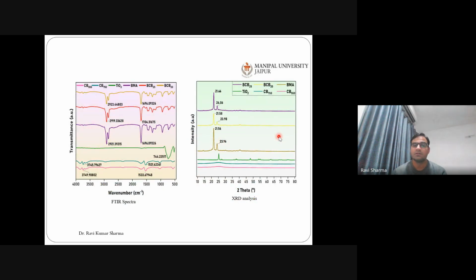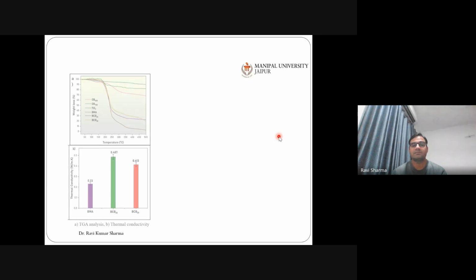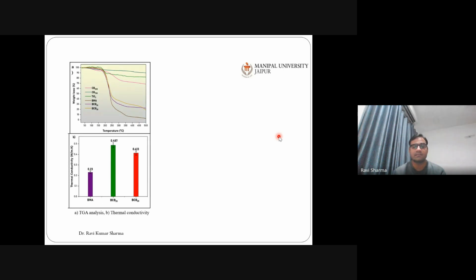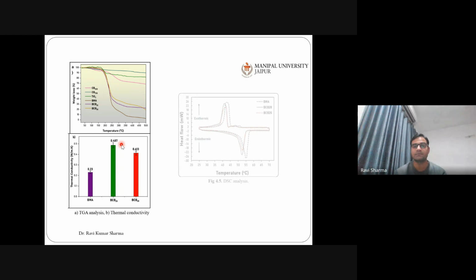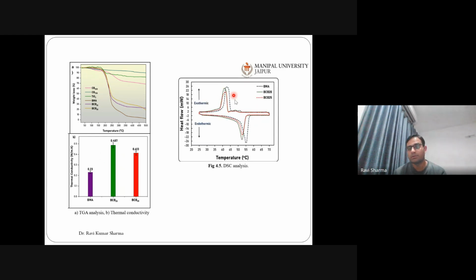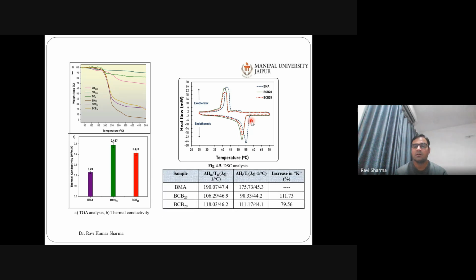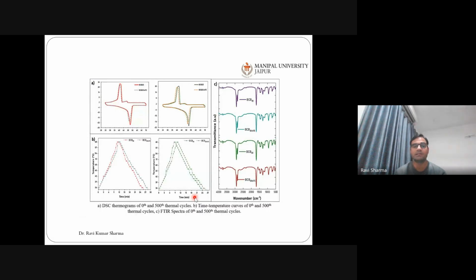But yes, this is another work we carried out very recently. It's already published, and this work gave a very fantastic result. The thermal conductivity was enhanced, almost doubled again, from 0.23 to 0.487, and the thermal properties were also very nice. The latent heat of pure PCM was 175, and the composite PCM was 98 and 111.17 for different percentages of porous materials.